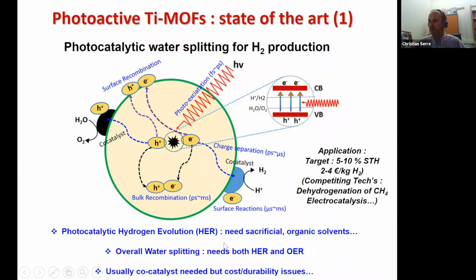Usually in photocatalysis, especially for hydrogen, they use sacrificial agents, so electron donors, like an alcohol or an amine. This is called hydrogen evolution. But the best case would be overall water splitting, where you can do both hydrogen and oxygen evolution. And in the field of porous solids, it is rare that you can rely on a single MOF. You usually need a co-catalyst, or at least 2 metals in the same structure, to have overall water splitting. And for instance, if you look at perovskites, the best materials so far are perovskites, and they rely on the addition of noble metal,